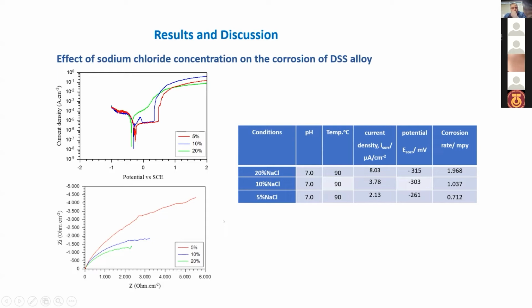Further investigation was also done by using electrochemical impedance spectroscopy, and this scanning impedance spectroscopy shows the Nyquist plots obtained in the solution in the 3 concentrations of chloride. The Nyquist plot is a plot of real impedance versus imaginary impedance. And the bigger the radii of the arcs are, the stronger the electrochemical impedance will be. So this test supports the results obtained in the potentiodynamic polarization.